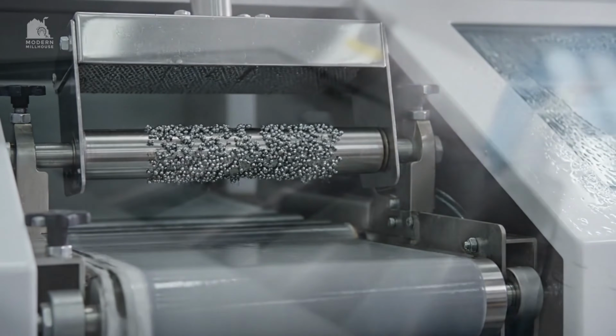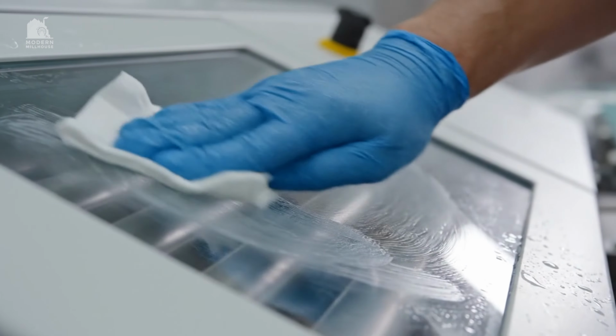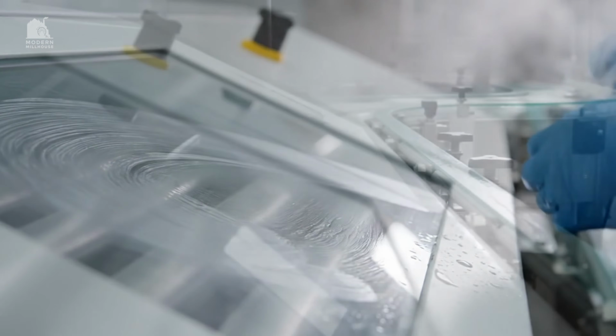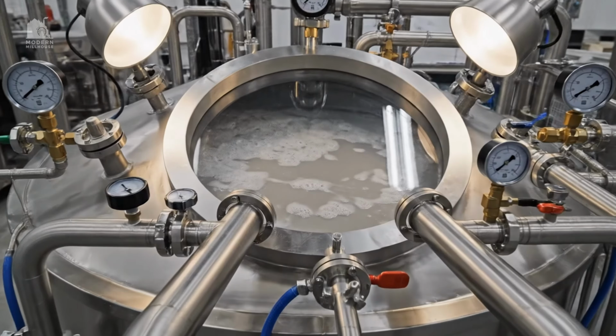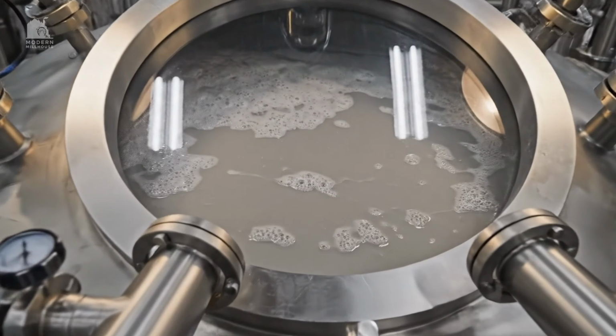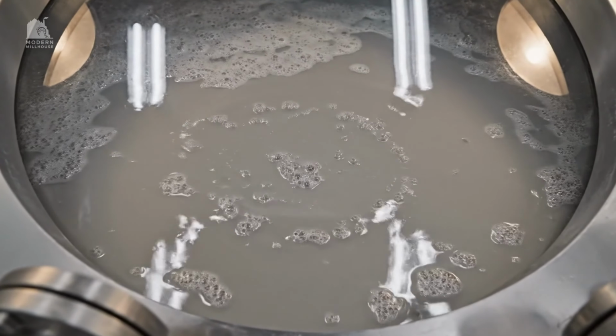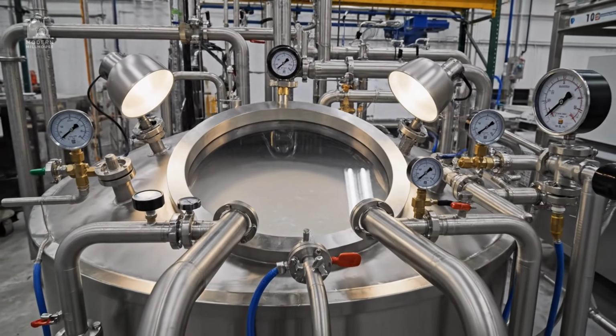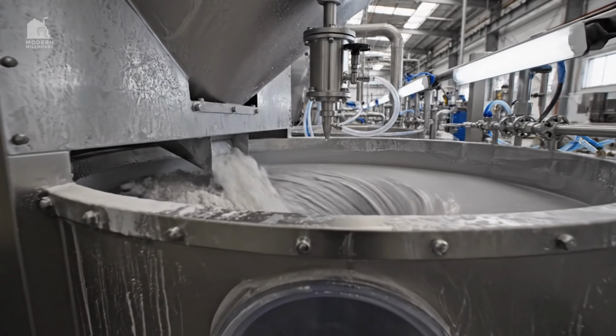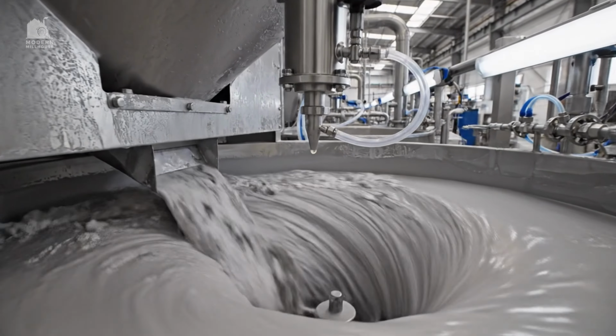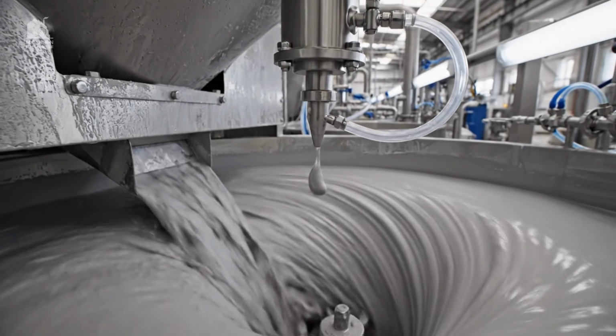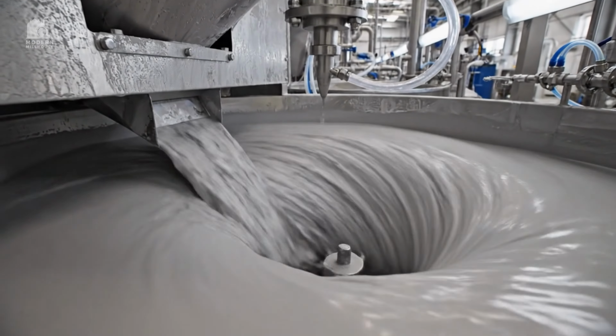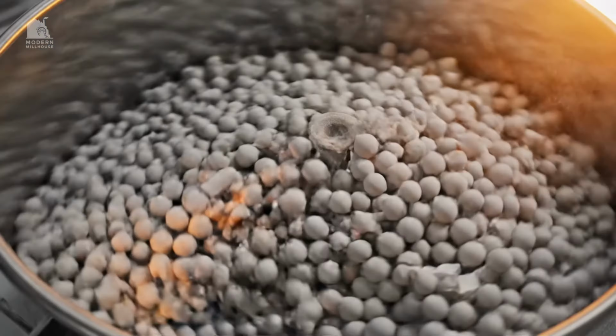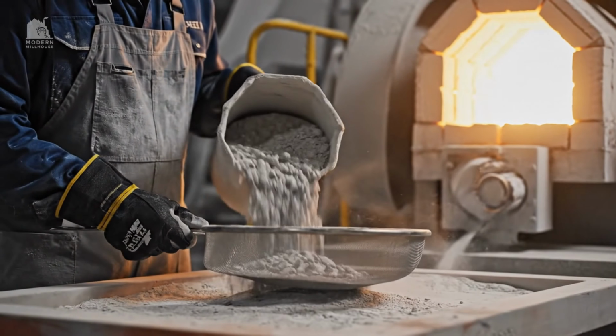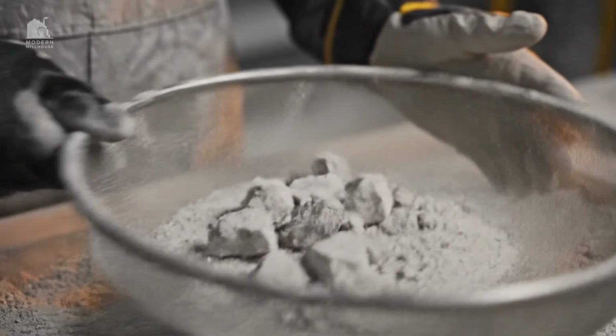Operators don't guess when milling is done. They sample the slurry and test it. They check viscosity, because a slurry that is too thick won't pump well and won't spray dry consistently. They check density, because too much water wastes energy and changes granule structure. They check residue through sieves, because oversized grit can become a weak point in a tile.